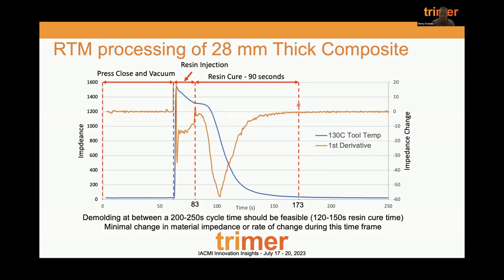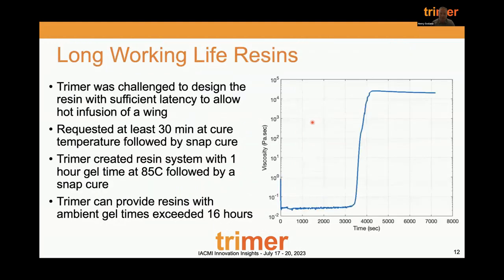You can see that the derivative has gone back to 0 here. The derivative's on the right-hand side, and that's showing that we're curing in about 90 seconds. It's 8 times faster than the current state-of-the-art epoxy being used for this part. So really, we can do thick parts and thin parts very quickly. Kind of a game changer for high-rate composite manufacturing.